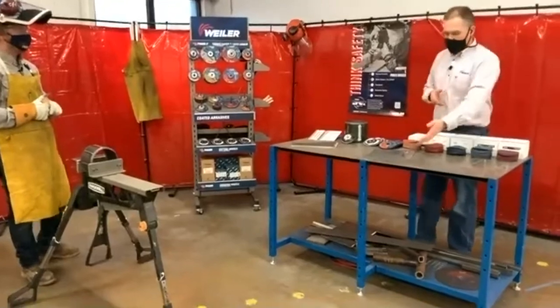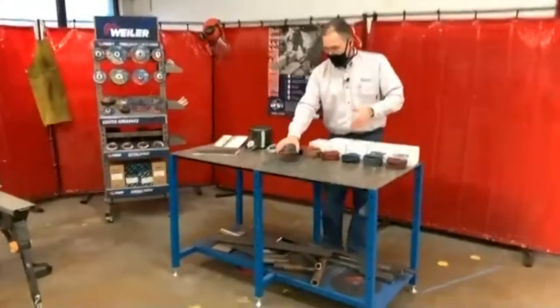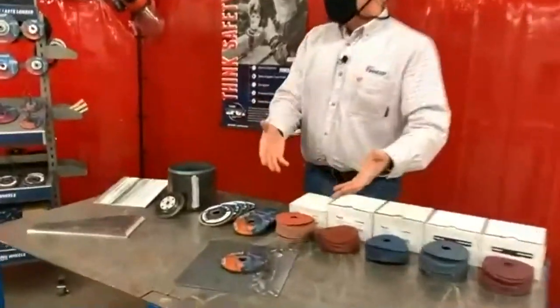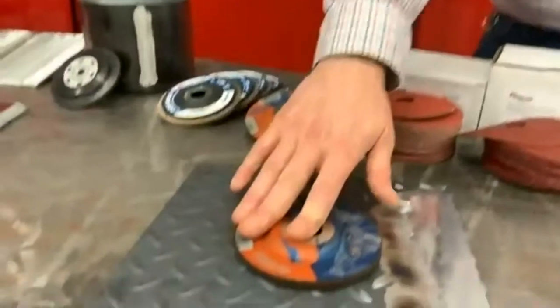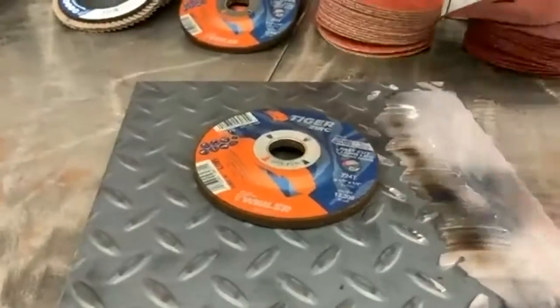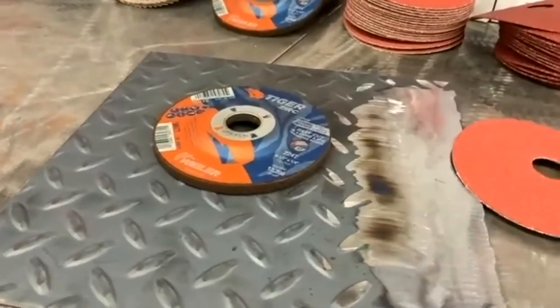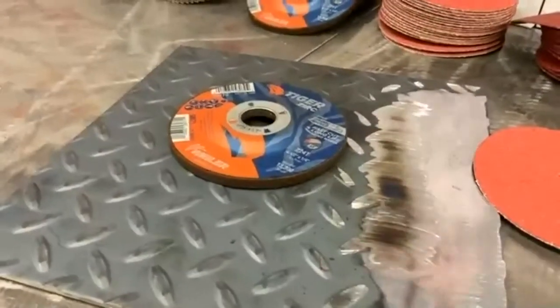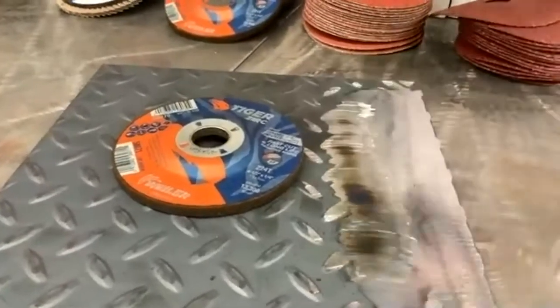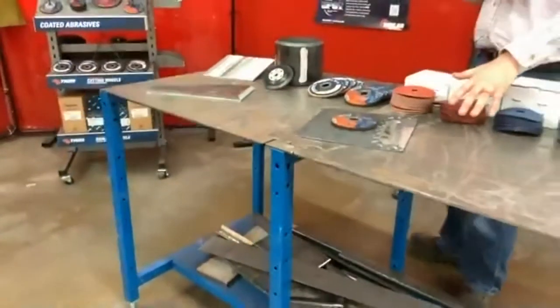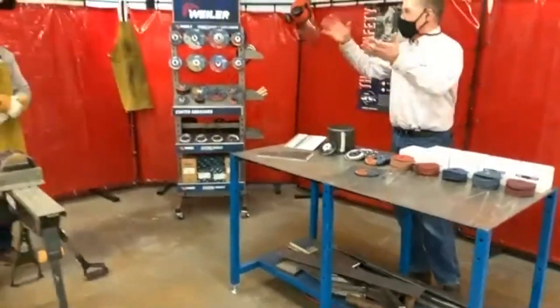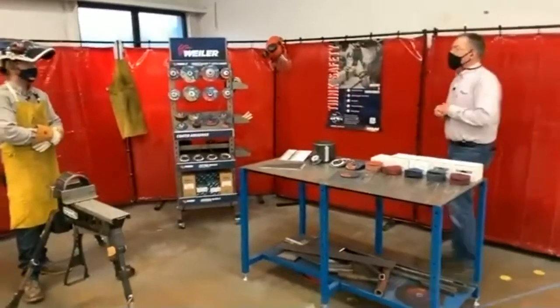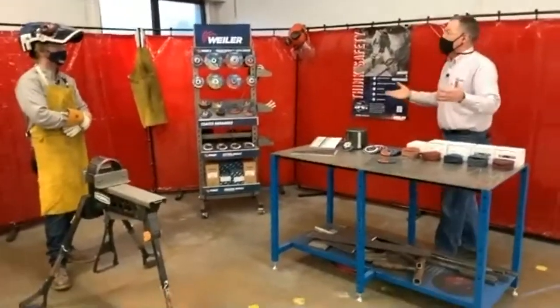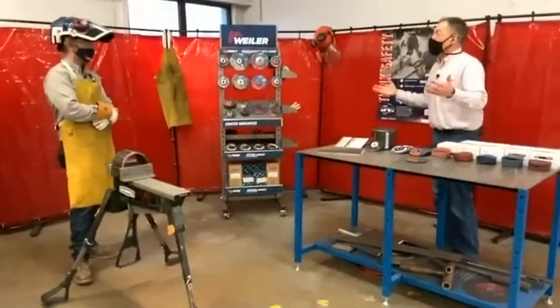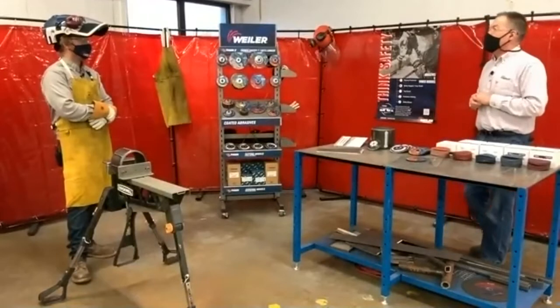And you know, Chad can zoom in and show us the difference between a comparable grinding line with a typical grinding wheel on a thinner gauge material versus that top coated resin fiber disc, and the significant difference in the same amount of time in heat discoloration, right? So that cooling aid, think of spraying PAM on a fry pan, right? It's going to do several things. We'll talk about that in a little bit in the scope of aluminum and soft materials. But one of the main benefits is the ability to keep grinding temperatures cooler and ultimately eliminate that heat discoloration that can also require a secondary operation or a secondary product to come in and actually clean up and finish the part. Exactly.